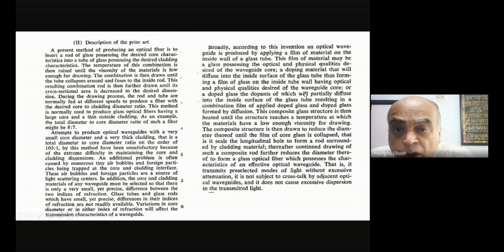Or a doped glass, the dopants of which will partially diffuse into the inside surface of the glass tube, resulting in a combination film of applied doped glass and doped glass formed by diffusion. So what they're saying is, I might actually have a glass which has an incomplete level of doping, and then I complete the rest of the process through the diffusion of the dopant into the glass.